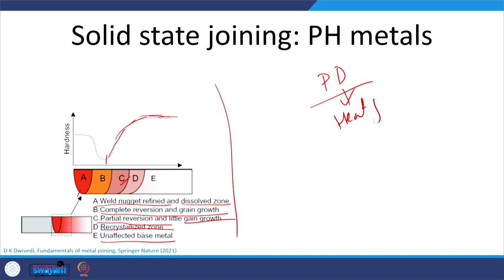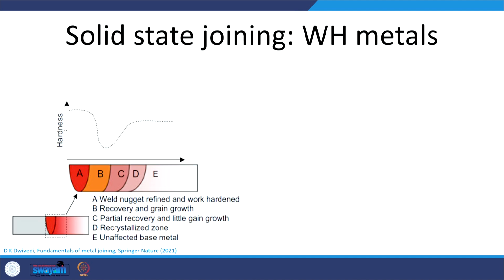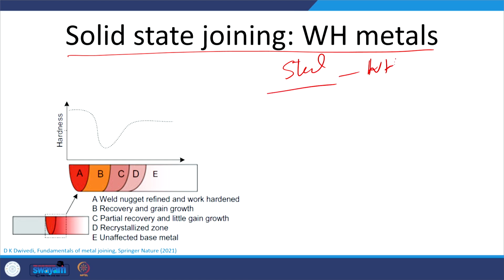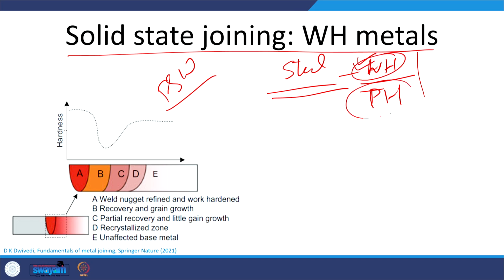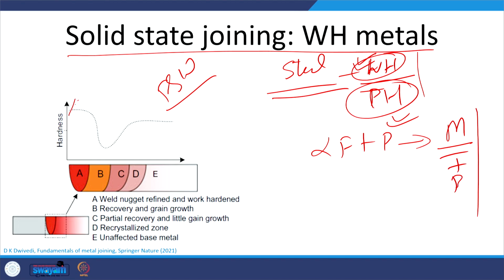where significant plastic deformation is involved, coupled with heat generation, enough heat generation which is able to cause recrystallization of the metals. If we talk of the solid state joining process associated with work hardening metals, then consider the kind of metallurgical transformation that can occur. Say, ferrous metals, if we talk of steels, then they also show reasonably good work hardening characteristics coupled with transformation hardening. So, solid state joining like FSW of ferrous metals causes significant work hardening of the weld nugget area coupled with transformation assisted hardening, because initially we may have ferrite and pearlite at room temperature, but the weld thermal cycle imposed during welding usually leads to the formation of martensite coupled with some pearlite, and therefore we get significantly higher hardness in the weld nugget area of ferrous metals.